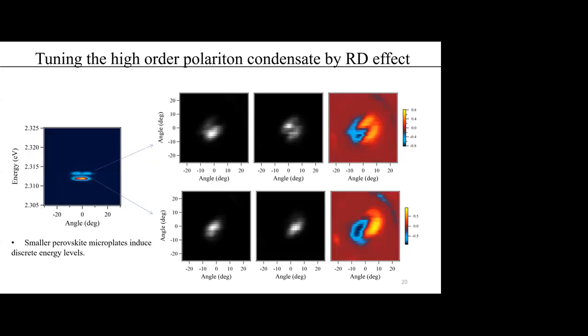In a smaller perovskite microplate within the same microcavity, we can observe polariton condensation with discrete energy levels due to the finite size of the sample. Here we observe two discrete energy levels when the voltage is 0. One energy level is the ground state, and the other level corresponds to one of the dipolar modes. At the voltage of 4.5 volts, we can see both the ground state and the higher order polariton condensates are split by the Rashba-Dresselhaus effect in the far field. Based on this, we can investigate further, like bistability or multistability, using these smaller perovskite microplates later.